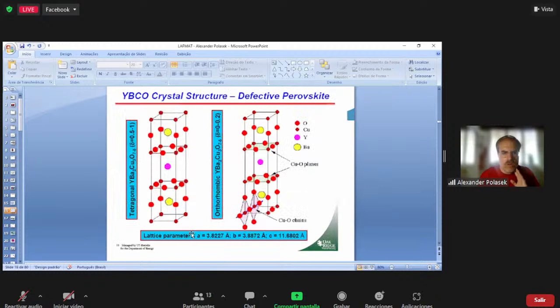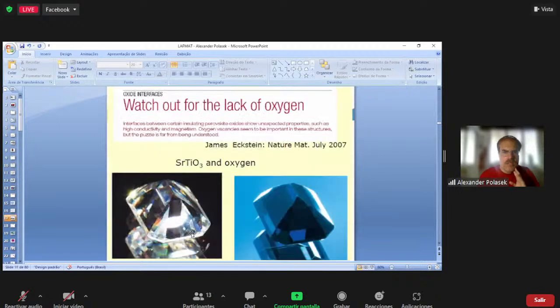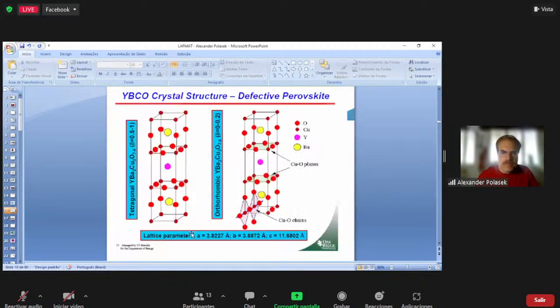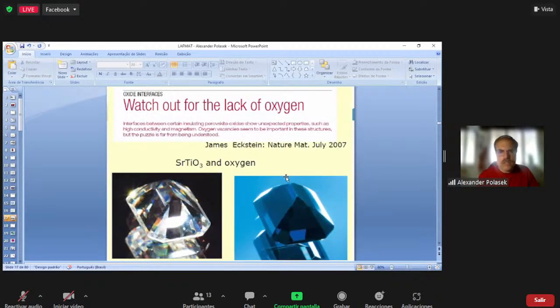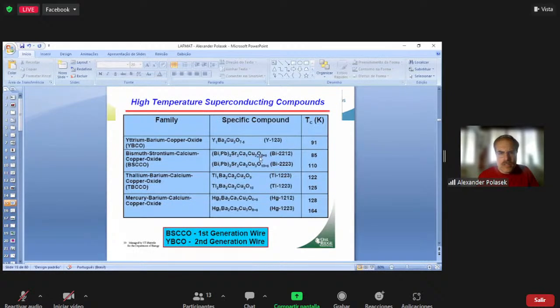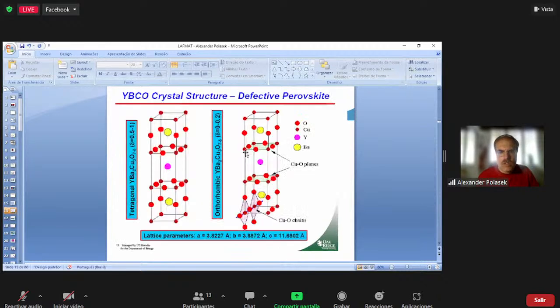This is the typical crystal structure of YBCO, as is well known. It's a defective perovskite. And another important thing: as I told you, the current is anisotropic because it flows mainly through these copper oxygen planes in the crystals. And so you have to align the grains in this direction. And these formulas are not really stoichiometric. Can you see a small delta here? You have deviations from stoichiometry, and small deviations cause a lot of difference in the final critical temperature.